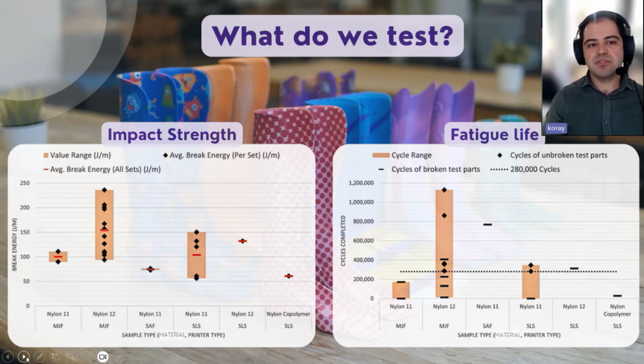When we think of the impact strength, it's really the amount of localized force that the material can undergo without cracking. With 3D printed polymers, it's all about preventing the crack from forming in the first place. If you can prevent it from forming, then you're going to prevent it from actually propagating and running through the material and eventually cracking.